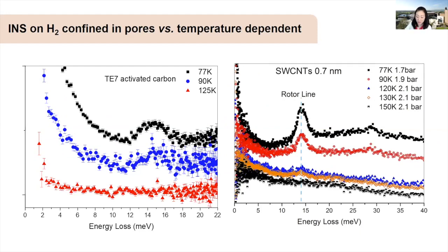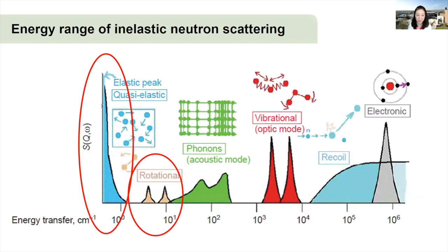Another interesting, surprising phenomenon in the neutron scattering experiments is we found the hydrogen confinement is temperature dependent. It's not surprising to find that, but what surprised us is, if we see the left figure, the immobile or solid hydrogen is maintained at a temperature as high as 90 Kelvin and it disappears at 125 Kelvin. A single carbon nanotube shows the ability to immobilize hydrogen at a temperature up to 130 Kelvin. If you see this orange diamond, it disappears at 150 Kelvin, which means all the solid-like hydrogen is mobile at 150. So this temperature is pretty high for hydrogen molecules.